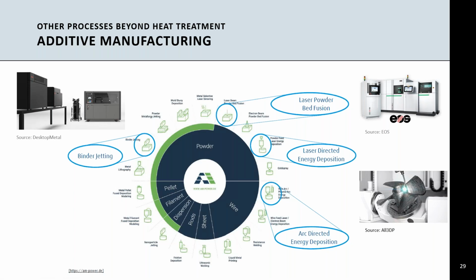So if you see here, some of the processes that Linde assists with are binder jetting, laser powder bed fusion, laser directed energy deposition, and then arc directed energy deposition. As demand for the additive manufacturing process has been steadily increasing, so have the many enabling technologies, including laser metal fusion, laser metal deposition, selective laser sintering, wire arc additive manufacturing, thermal spraying, and electron beam melting. Products manufactured with these processes and technologies are typically forged, heat treated, or sintered to achieve the quality, finish, and mechanical properties desired. Process gases play a vital role in every step of the AM fabrication chain.